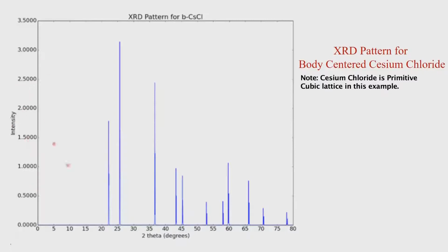The XRD pattern will appear as a relative intensity versus 2 theta in all experiments which you perform in a normal diffractometer. And therefore, the 2 theta degrees which we plot in the x axis will represent various 2 theta values. Now, these 2 theta values are the ones which will tell us the corresponding d values, because we use the formula 2d sin theta equals lambda, where lambda is the wavelength we have used. So, obviously, this pattern will be different for different wavelengths.